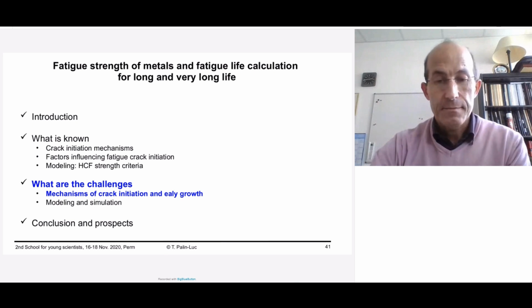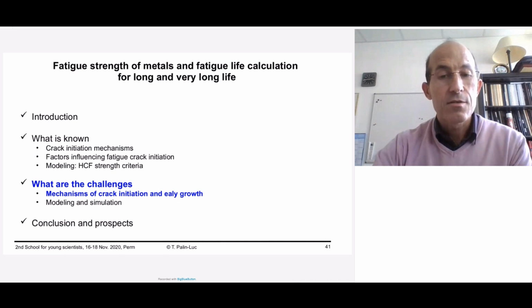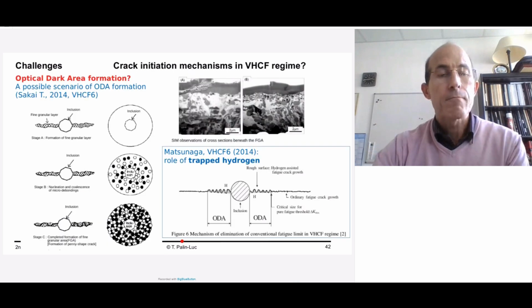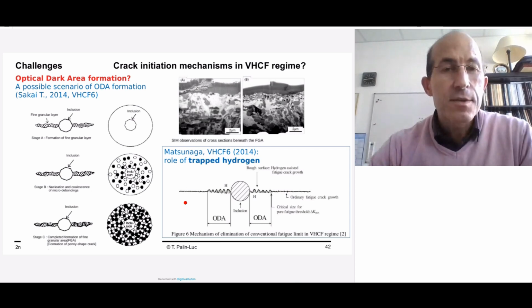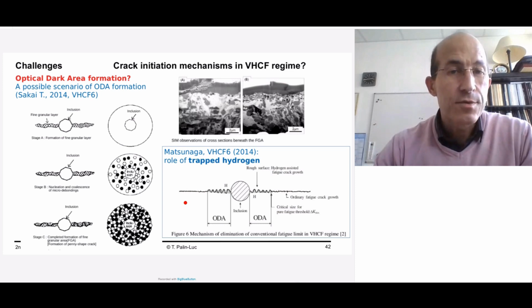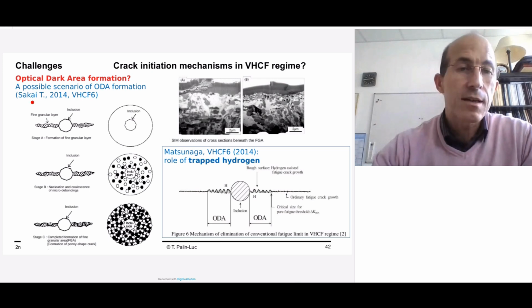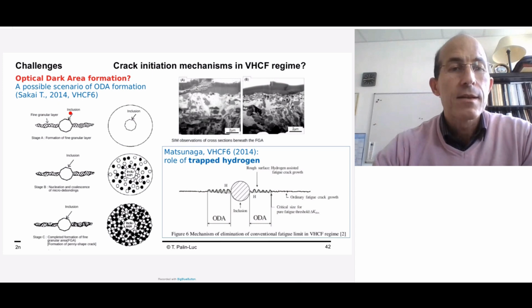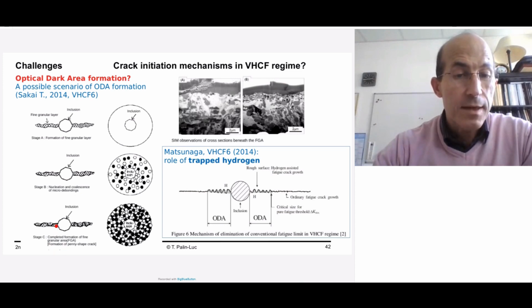What are the challenges? First, I'm talking about the challenges in order to better understand the mechanisms of crack initiation and the first stages of crack growth after initiation. I told you that in the gigacycle regime, when there is an inclusion responsible for the crack initiation, in the famous fish eye features, there is an optical dark area around the internal inclusions. To explain that, a possible scenario proposed by Sakai in 2014 is the following. Around the inclusions, there is a fine granular area which is formed because of micro debonding between the inclusion and the matrix. And this micro debonding, because of repeated cyclic loading, will create accumulation of microplasticity and the creation of a fine granular area because of recrystallization.